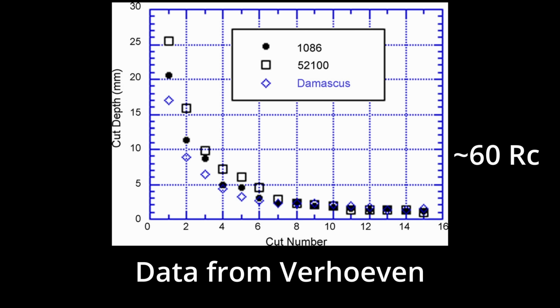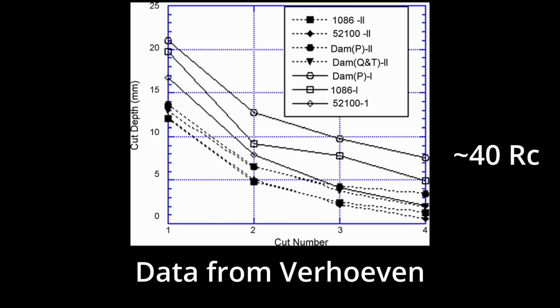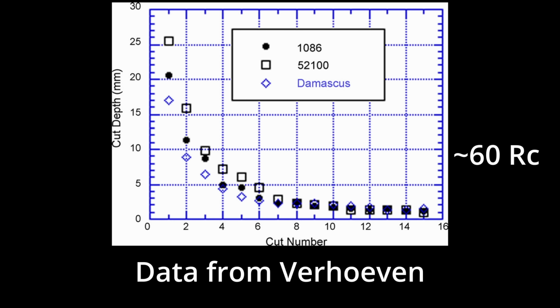Dr. Verhoeven also did a Catra test before with Wootz, AEBL, 52100 and 1086 steels. And there were some interesting things there because in that study at 60 Rockwell comparing with 52100 and 1086, Wootz did the worst. But when tested around 40 Rockwell, the Wootz did the best. Now, I looked at this study and I was a bit mystified by it, but I think what happened in the study was inconsistent sharpening. Because if you look at cut number 1 in the Catra test, the Wootz Damascus was already the worst cutting steel. And so if the edge is not good at the start of the test, then of course it's not going to cut as much overall.